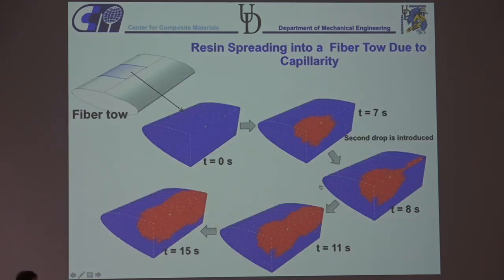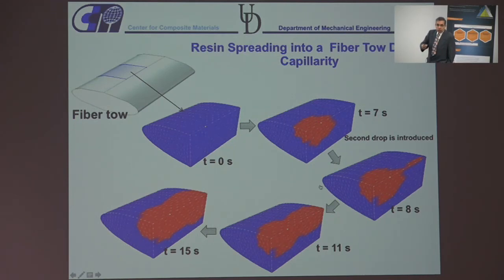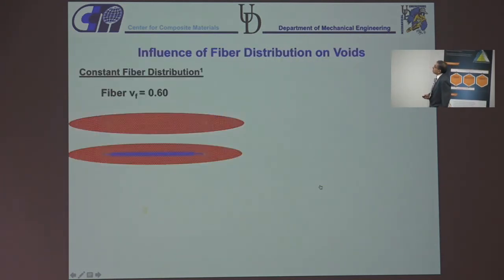So this also has advantages in, for example, additive manufacturing. So here is a case where you have a fiber toe going through an inkjet printer, where you can actually drop a fluid onto the toe, and you want to see how it spreads into the toe. So you drop it over here at time t equal 0, and you see it spreading a little bit. And then when you introduce the second drop, you see the interaction between the drops within the time scale. So it will give you an idea about how fast you should move your toe, how fast you should drop it, what should be the size of the drop, and so on. So we can model that with our own simulation.